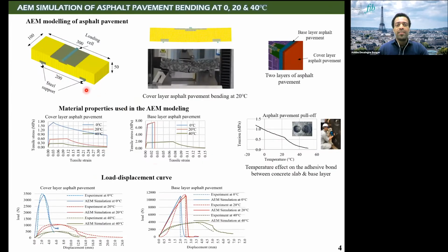So to understand the behavior of asphalt pavement at different temperatures and to set appropriate material behavior and other parameters in the numerical modeling, we carried out asphalt pavement bending tests at 0, 20, and 40 degrees centigrade. And this is the AEM modeling of the asphalt pavement. It is 3-point bending. This is how the bending was carried out, simulation and experiment.